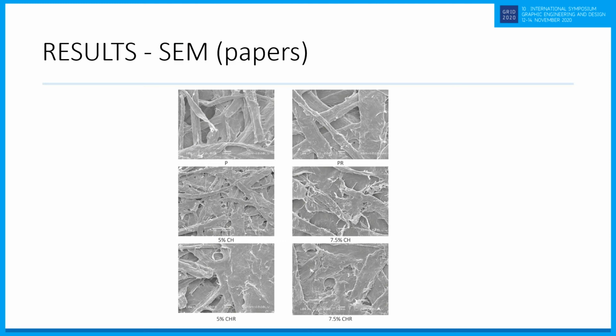The surface of the sample papers showed a smoother and more uniform surface for papers with fillers, compared to the samples without fillers, like only P and PR samples. A comparison between paper sheets with the used fillers but different concentrations proved their effect, which is consistent with improved mechanical and water barrier properties. The absorption, thickness, moisture, and roughness of the paper with fillers have a great influence on the properties of the chemical structure.